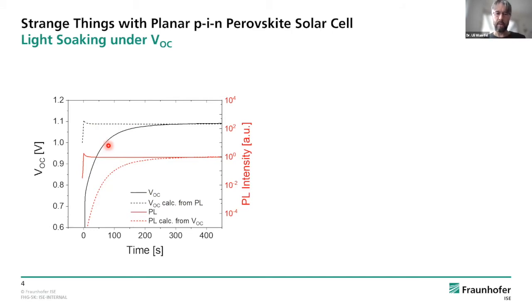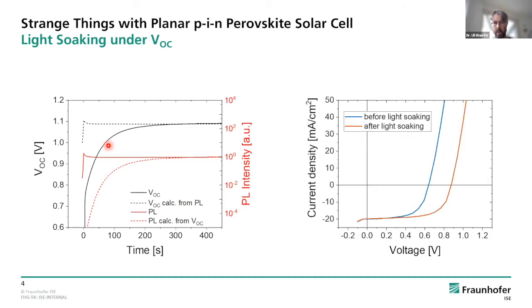It's a very, let's say, puzzling result. Interesting is, of course, also that the solar cell that behaves, let's say, very badly recovers quite well under illumination and open circuit conditions. But what, let's say, most caught us is this obvious decoupling between the photoluminescence intensity and the open circuit voltage. We also measured the normal current voltage characteristic. I'm sure you have seen such a curve in the morning maybe, before and after light soaking.